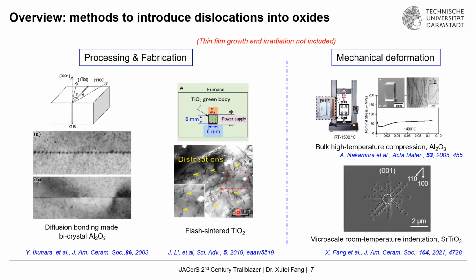So when we come to mechanical deformation, it has been well known in history that high temperature deformation has been widely used to achieve plastic deformation of ceramic materials, being either single crystal or polycrystal samples. Here is one example showing single crystal alumina deformed at 1400 degrees C. As you can see, we can even achieve roughly 10% plastic strain without breaking the samples.